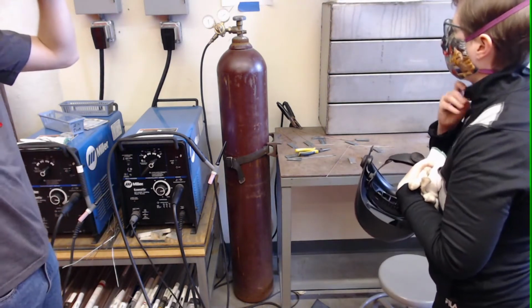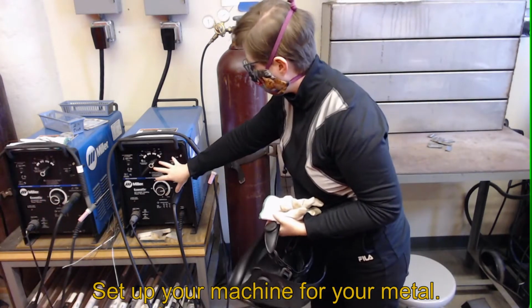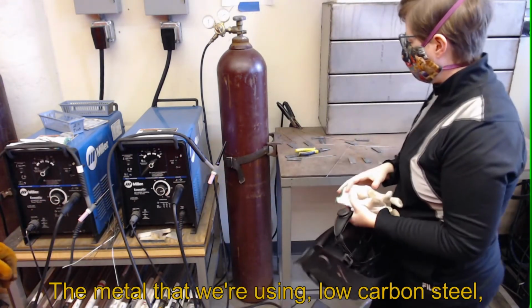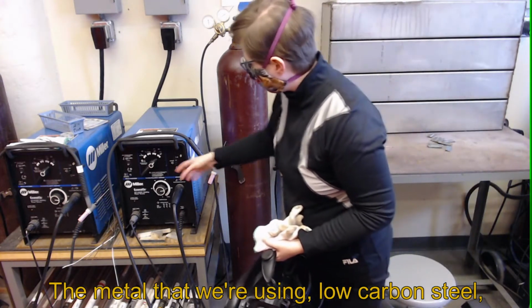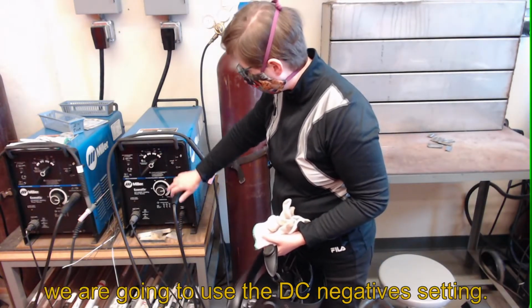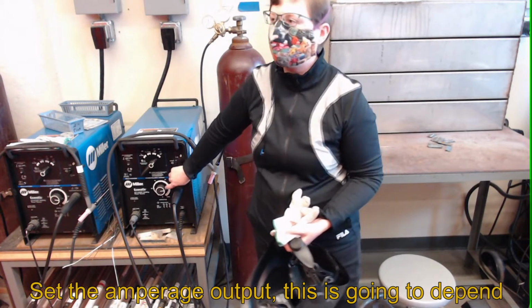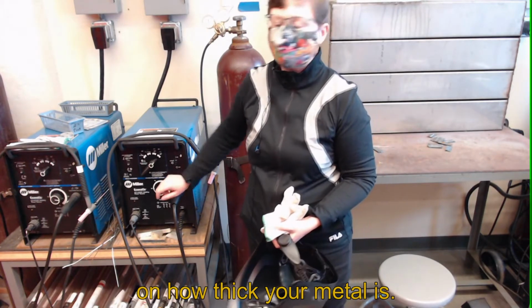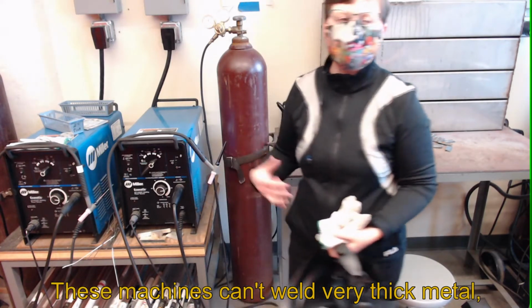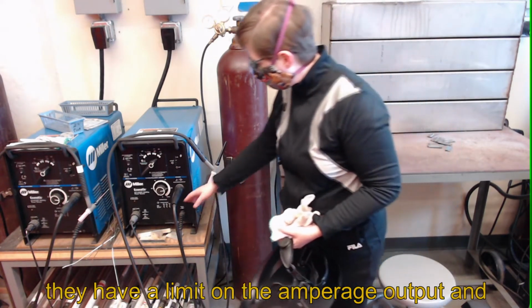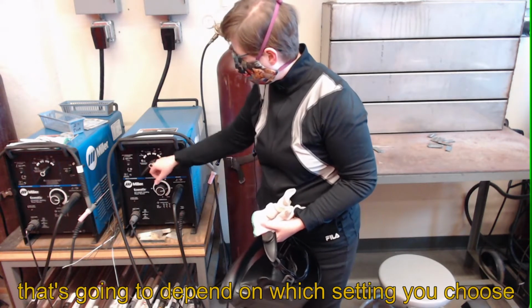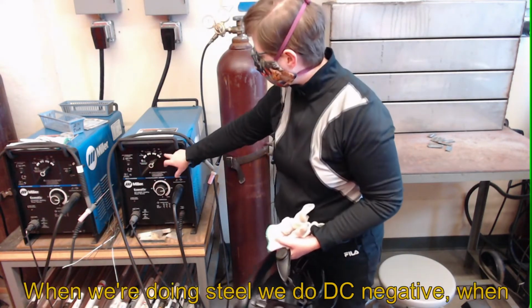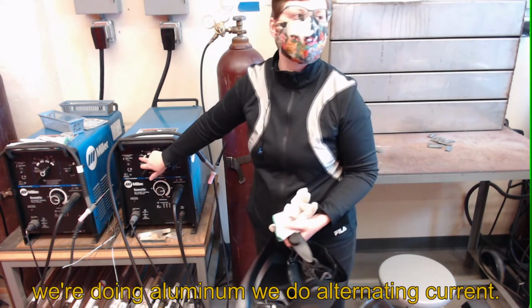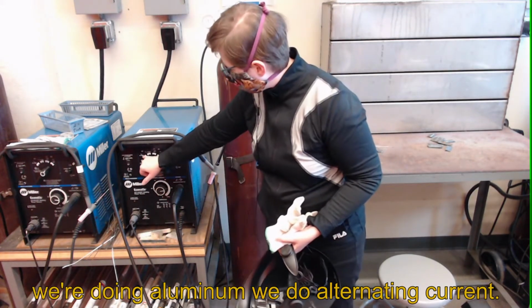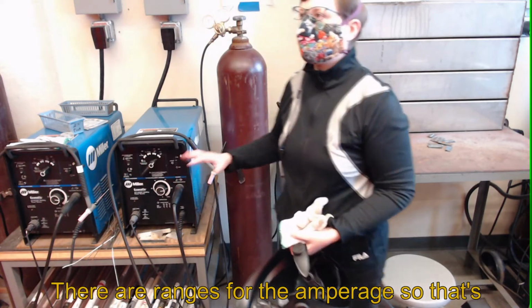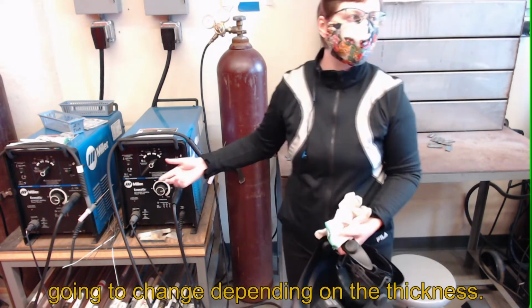So when you're welding, you set up your machine for your metal. The metal that we're using, being a low carbon steel, we're going to use a DC negative setting, and we're going to set the amperage output, and this is going to depend on how thick your metal is. These machines can't weld really thick metal. They have a limit on the amperage output here, and that's going to depend on which setting you choose. When we're doing steel, we do DC negative. When we're doing aluminum, we do alternating current. And then you'll see there's ranges for the amperage. That's going to change depending on whether you have a thin piece or a thicker piece.